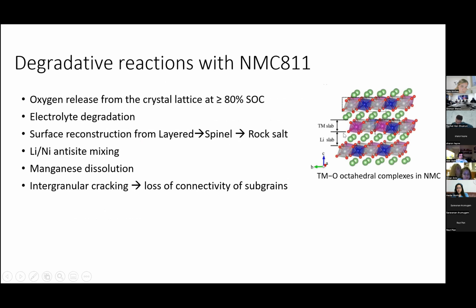Especially here, as you see, in the structure the red atoms are the oxygen atoms. There is a release of oxygen atoms when we try to extract approximately 80% of the lithium from the cathode material, which will lead to electrolyte degradation because oxygen is highly active, and electrolytes are majorly organic species. As a result, with the reaction of oxygen, they form organolithium species. And not only that, there is surface reconstruction from layered to spinel and further to rock salt because of the loss of oxygen.